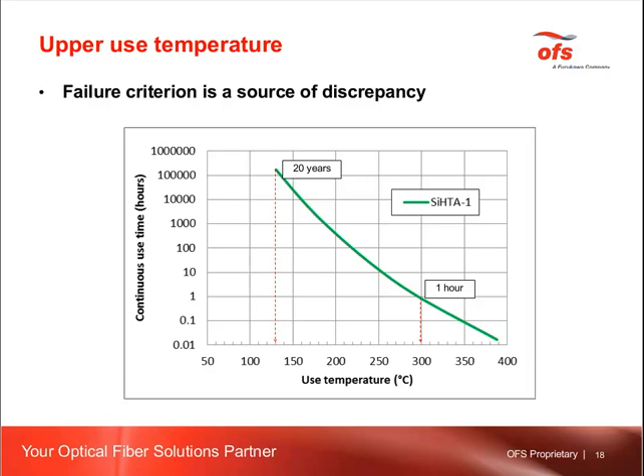Unfortunately, this comparison shows that there is a big room for speculation. Depending on the failure criterion and depending on the usage time, we can say for the same coating that it is good up to 130 degrees C, or it is good up to 300 degrees C, or to any other temperature. And unfortunately, some manufacturers of optical fibers can say that this coating is good up to 130 degrees C, and the other manufacturer will give a different number. Once again, it is a room for speculation. Ideally, we should provide here what the criteria were and what continuous use time is in mind.